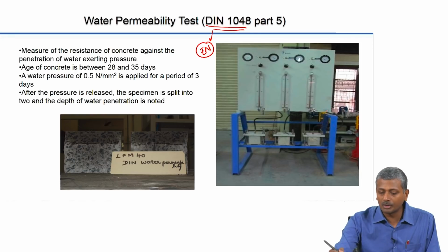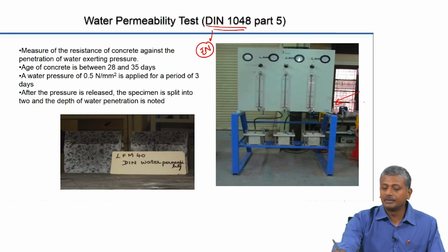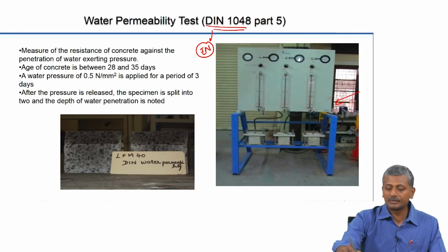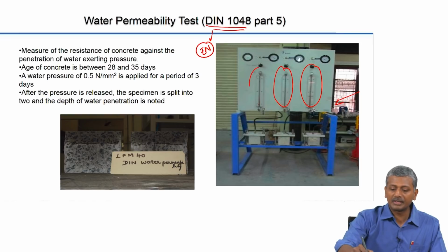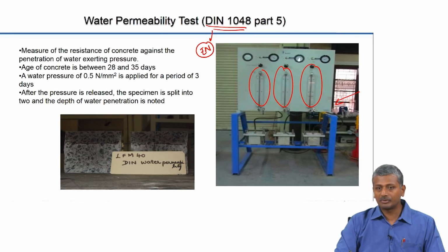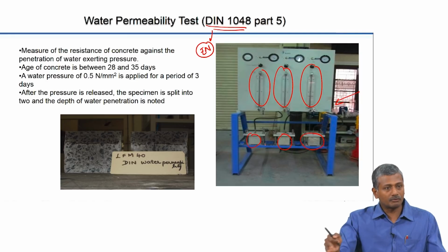So this is the water permeability apparatus that is there in our laboratory. Here this graduated tube tells you the amount of pressure that you have set up for the water in the system, and this is your concrete specimen, which is tightly sealed on the top and bottom to ensure that there is no leakage of the water from the sides.